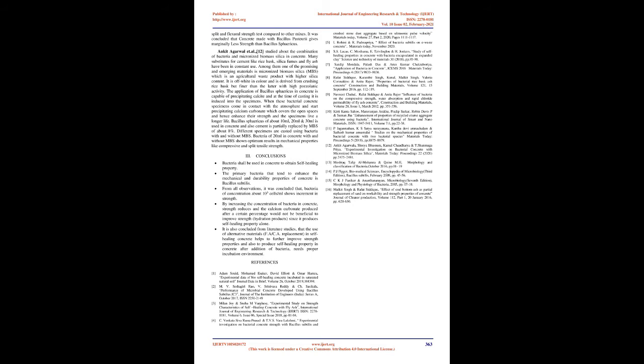Navneet Chahal et al. reported the results of an experiment carried out to evaluate the influence of Sporosarcina pasteurii bacteria on the compressive strength and rapid chloride permeability of concrete made with and without fly ash. Cement was replaced with 3 percentages, 10%, 20%, and 30%, of fly ash by weight. Multiple cell concentrations, 0, 10^3, 10^5, 10^7 cells/ml, of bacteria were used to make concrete mixtures. Tests like compressive strength, water absorption, and rapid chloride permeability were conducted at 28 days of age.